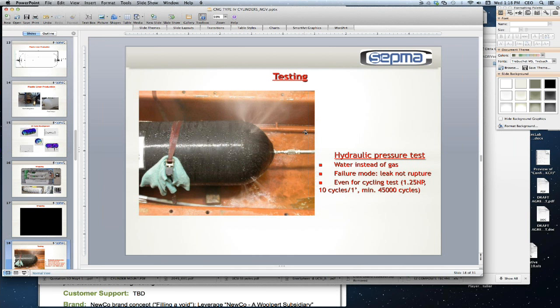But the real trick when you design these products is to design them not for catastrophic failure, but rather for a premature failure, if you will, through leak and not rupture. That minimizes the potential of turning the debris into projectiles if it was to explode. So this is a typical system, and this is done during cycling, back and forth, so increase the pressure, lower the pressure until we see failure.